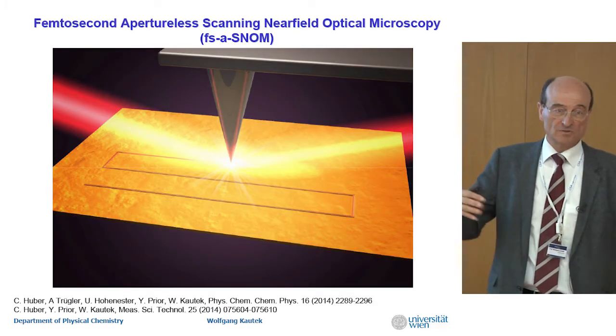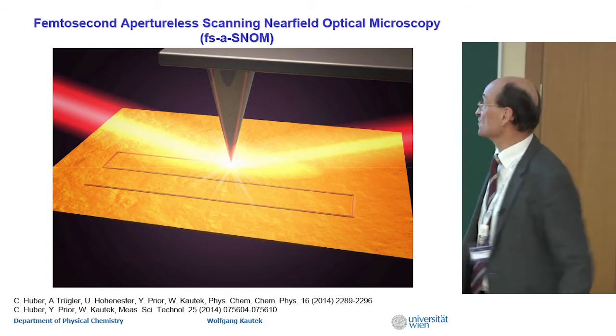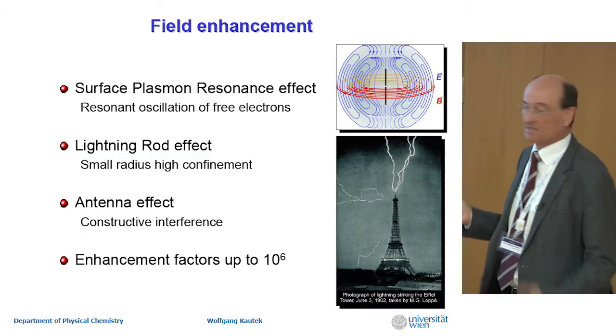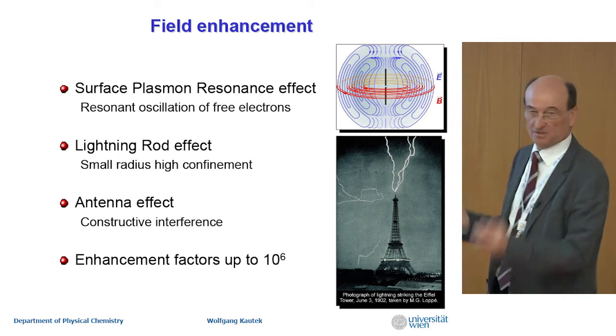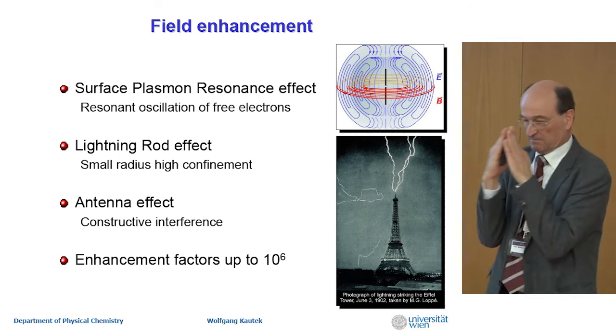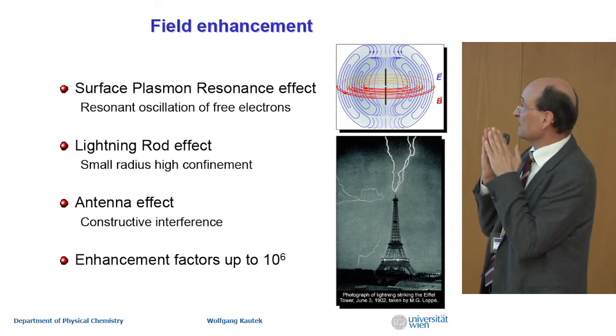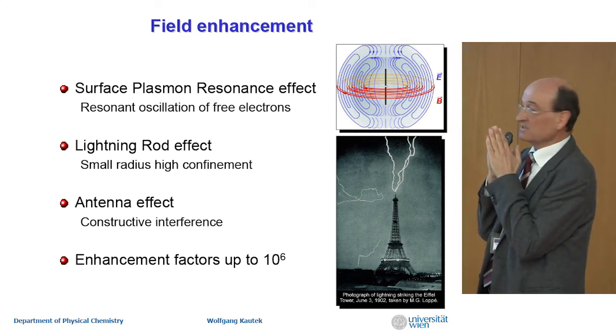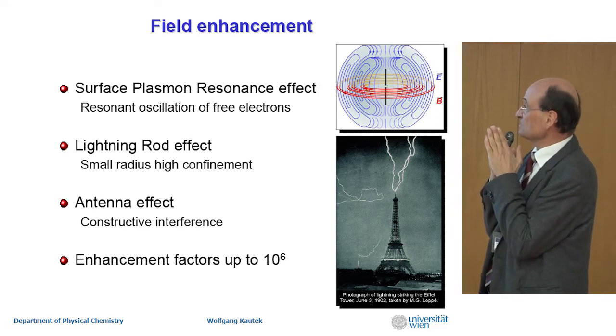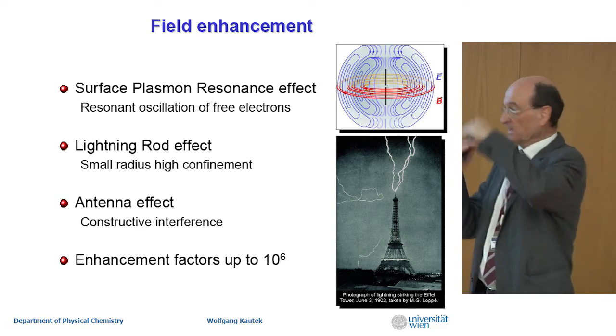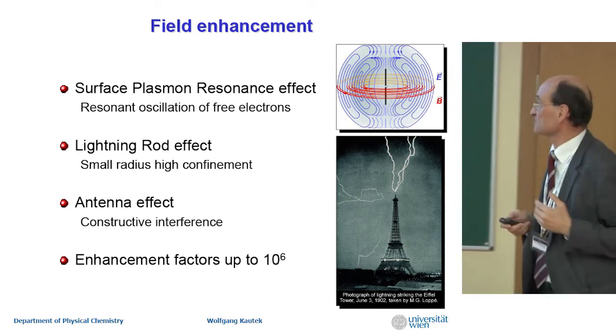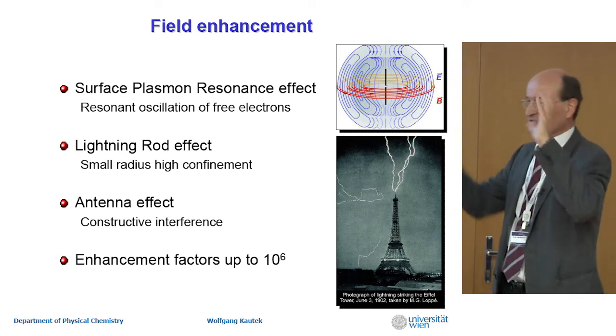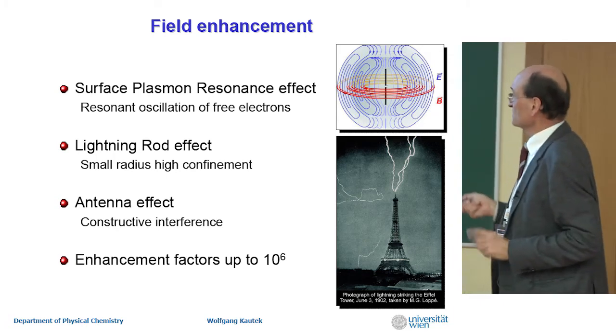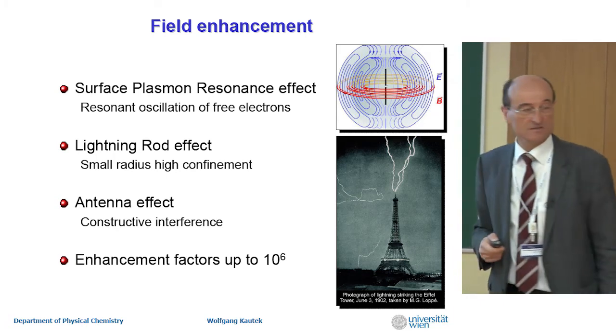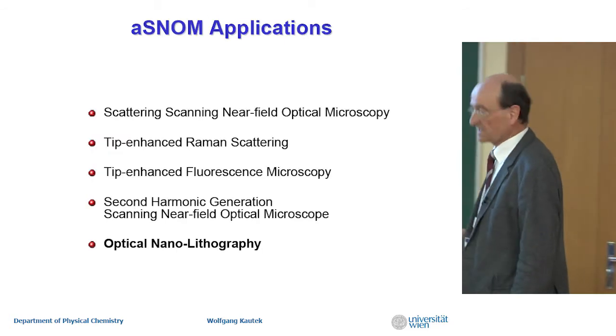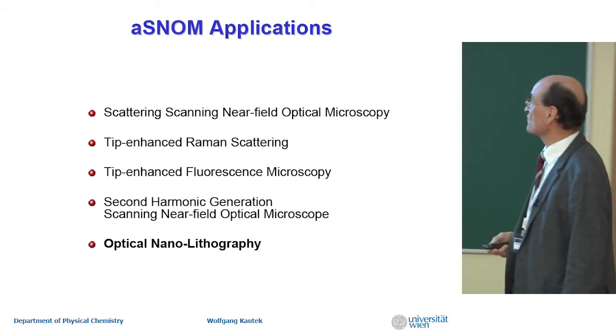So if you want to become finer, you have to play a trick on nature. And the trick on nature is based, in our case, on surface plasmon resonance effects. Then on the tip, you have a lightning rod effect, yeah? Small radius with high confinement. And the antenna effect is when there is a resonance, a constructive interference possible. And that depends on angles and material and so on. But you can expect enhancement factors at the tip of 10 to the 6. And that is nice to be used, for instance, in optical nanolithography.